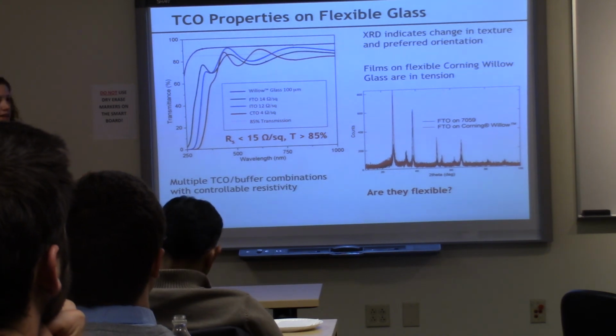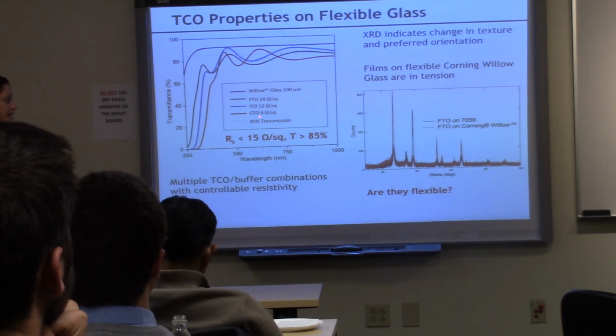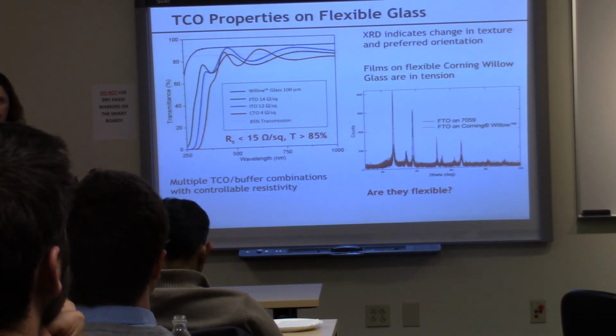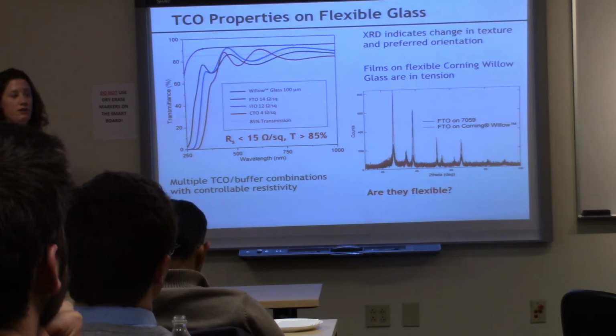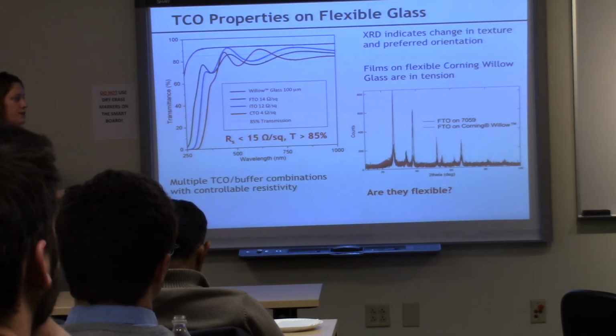And then cadmium stannate, which is an oddball contact, but we use it in CdTe because it's full of cadmium, and we always like having more cadmium. It also happens to be the best performing TCO known to humankind. So we were able to meet our optical and electrical metrics. We did some XRD to see if there was a difference in the films on rigid glass from the films on flexible